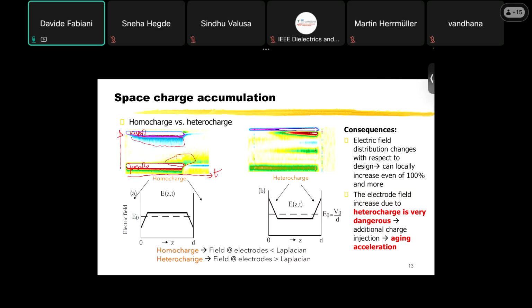This is homocharge. The homocharge can reduce the electric field with respect to the average field at the electrodes here and here, while it can increase a little bit the electric field in the middle of the material. Because of course, remember that the integral of the field is the applied voltage. So the applied voltage is still the same, but the local field can change due to the space charge accumulation.